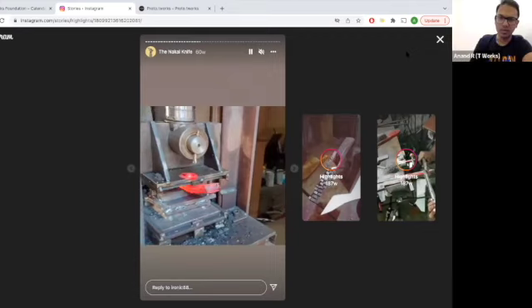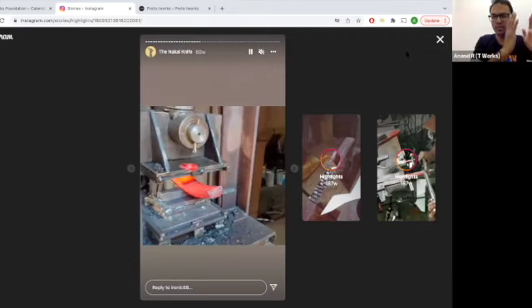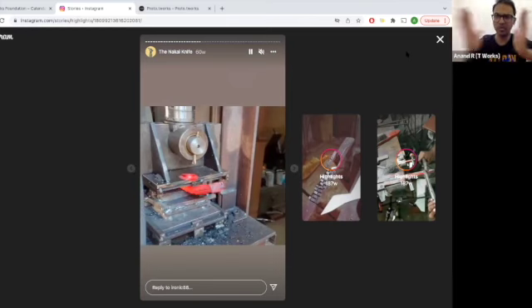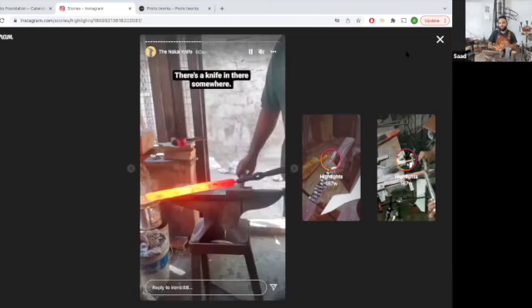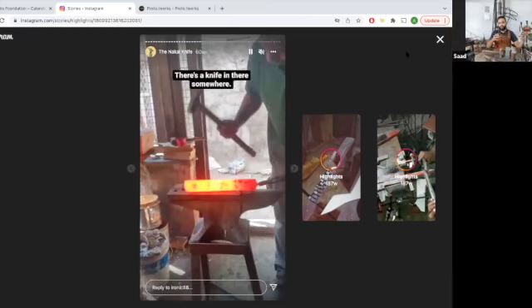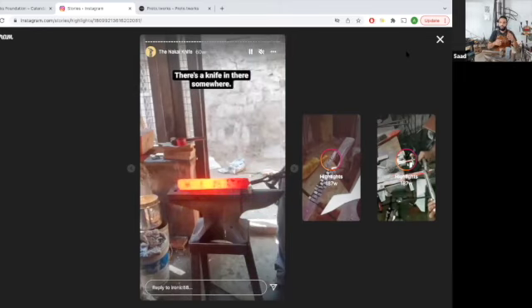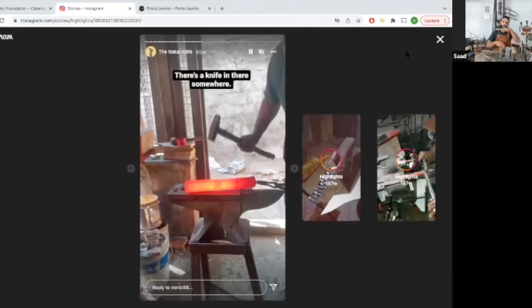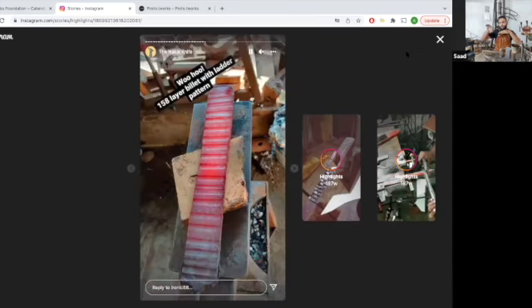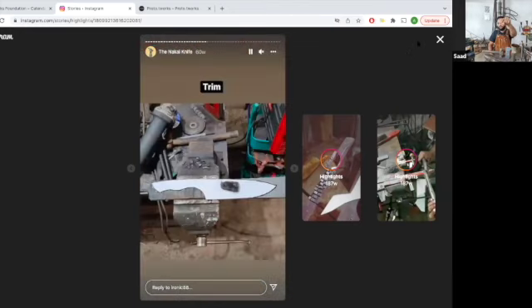And is that what you did, or you had 20 layers and then you put them together? No, it's more efficient to do it like 20 layers, stretch it out, and then fold it, and then keep continuing that way. You can also, depending on your pattern, so sometimes you have patterns that go one way and then another pattern that goes another way. So you can make a billet separately for this, make another billet for this. Now this is called a ladder pattern. So you can see I put these indentations within the billet.